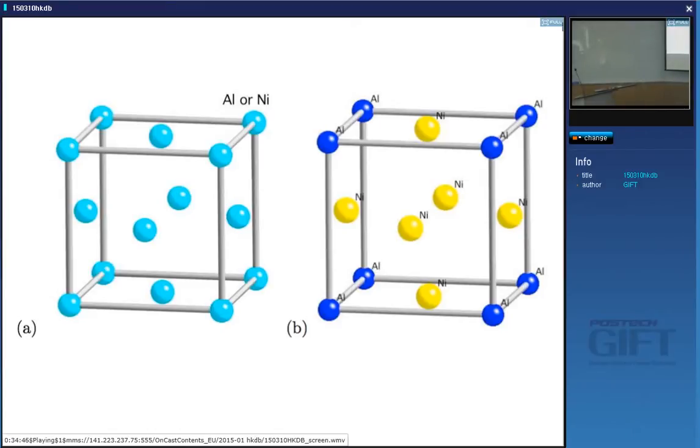So the lattice parameters are very close to each other. So these two kinds of structures fit very well together, and they are in a cube-cube orientation relationship. That means the edges of the cubes are parallel. Now that's very important because that reduces the interface energy between the compound and the disordered phase. Now why is it important to have a low interfacial energy when you're operating at high temperatures? Say you design your precipitates to produce strength, okay? If you're operating at 1400 degrees centigrade, why is it important to have a very low interfacial energy?